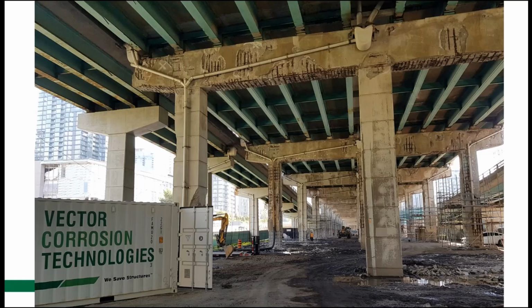So this is in phase 1 of the project that was referred to in the videos. And here's a picture of the existing or the pre-existing condition of the substructure units. And you can see that there's a lot of damage. This is before concrete removal. There's obviously delamination and spalling. You can see clearly signs the joints have been leaking, and it's led to issues with the substructure. So these are not pristine, brand new things that are just being touched up. They're in fairly rough condition from a concrete point of view anyway.